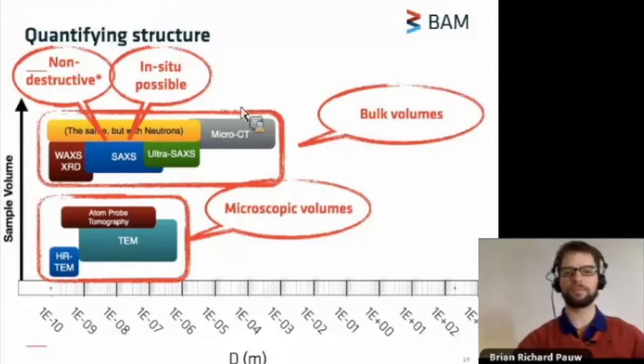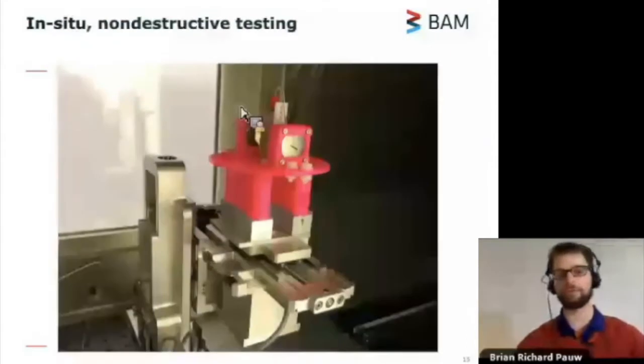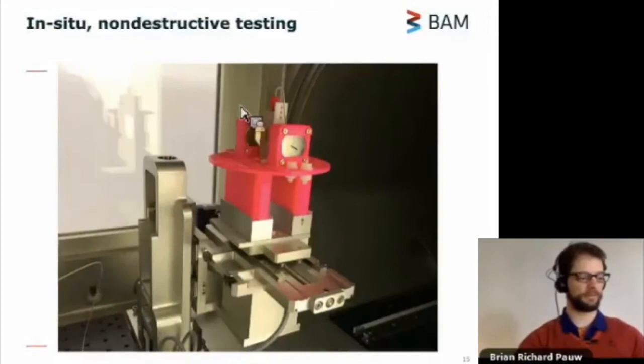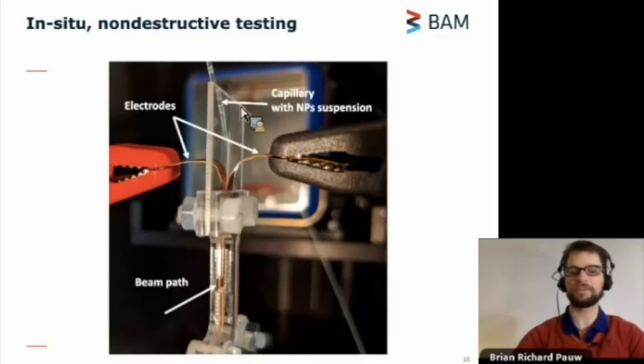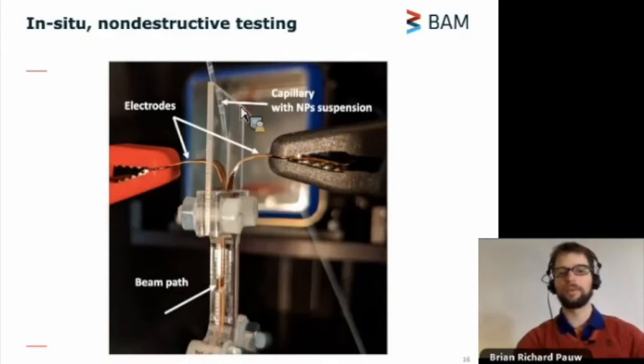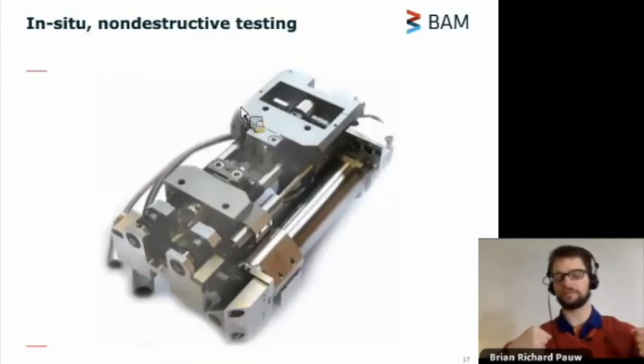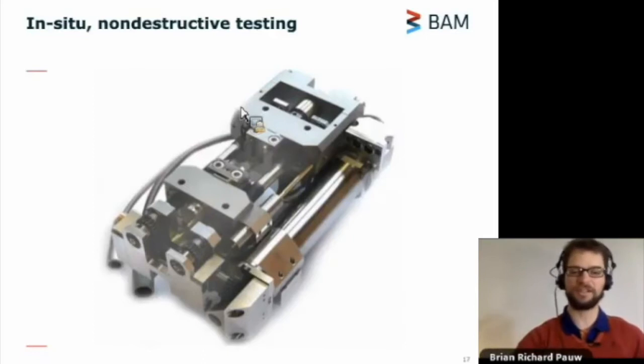Well, we can put your sample in a magnetic field. Here is an example with two very strong permanent magnets, which cause ferromagnetic particles to be affected by this field. We can put your sample in an electric field as well. In this case, the experiment didn't work out, but there are examples where electric fields have caused an effect in the sample or in the structure of the sample. We can have a small tensile stage in there, so we can pull on your sample, and if you pull on your sample, something in the structure must change.